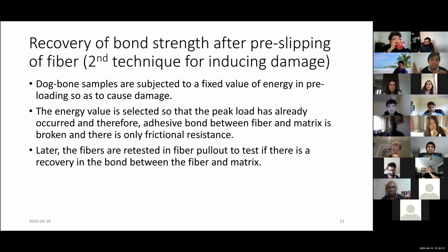So there is a slip that is occurring in the fibers. After the peak has occurred, I stopped at a certain value of energy, and I stopped at that every time so as to roughly induce the same kind of damage in all of the samples. So the adhesive bond is basically destroyed since I load it past the peak, and there is only frictional resistance left inside now.